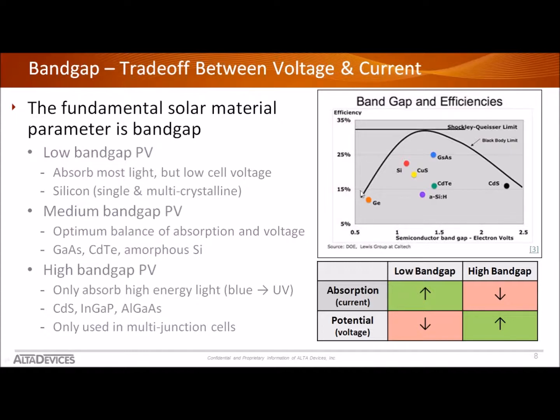And that's represented by the graph over here, where as your band gap gets larger, your peak efficiency peaks right in the middle, where cadmium telluride and gallium arsenide and copper sulfide are. And that is the material we work with, gallium arsenide.